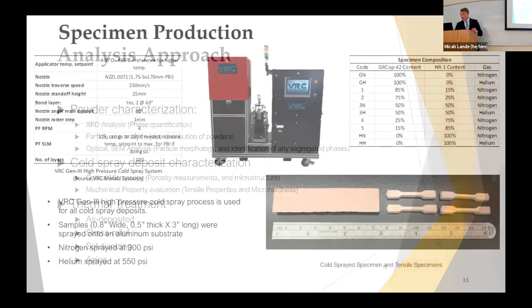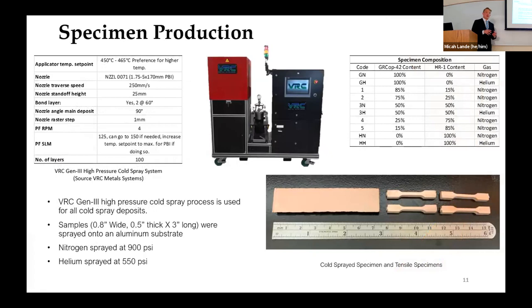So to start off with, all of these samples were manufactured by VRC, where they were all produced using a VRC Generation 3 high-pressure cold spray machine. And so they were all sprayed onto aluminum blocks, then water jet off and machined, and then we're left with this solid deposit, the solid structure like that. And then from there were water jet cut out into these tensile testing shapes, which were all about 3.5 centimeters long.